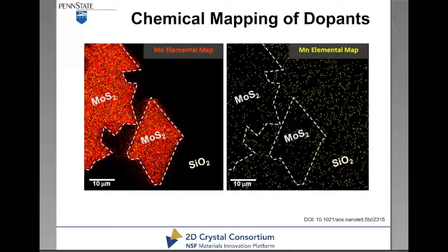So at 100 times, we're on the order of a third to a half of an eV in terms of the binding energy of excitons in these 2D materials. And what that leads to is a massive difference between what you think you have as a band gap optically, and what the true band gap is in the material.